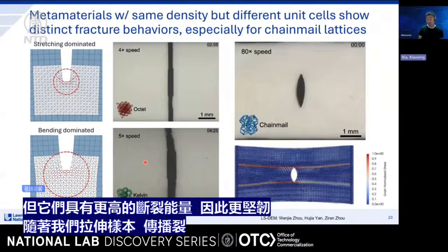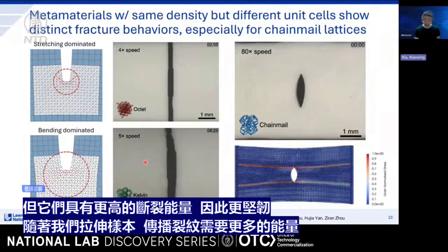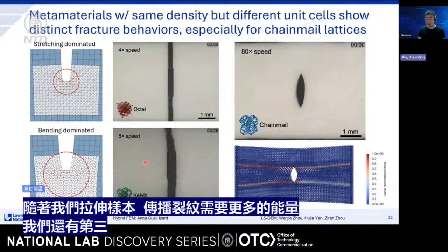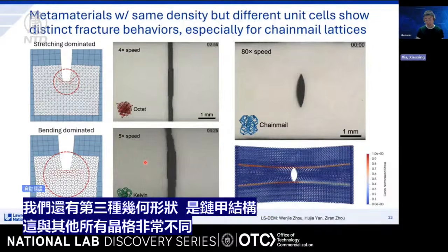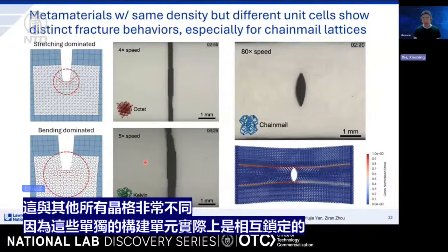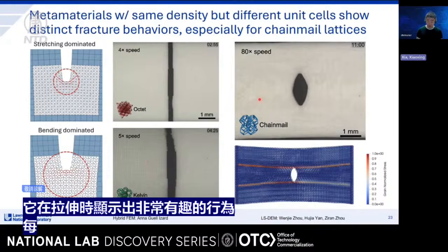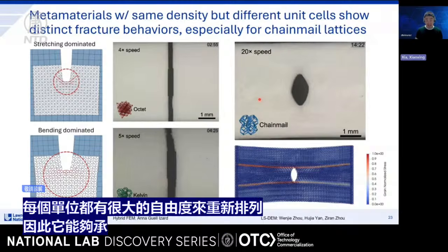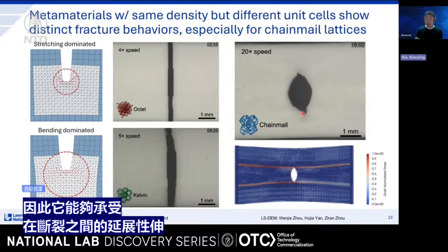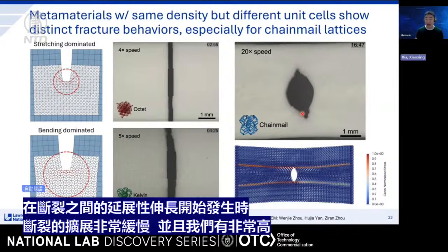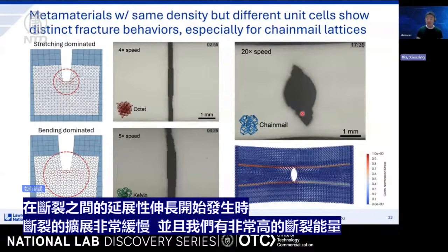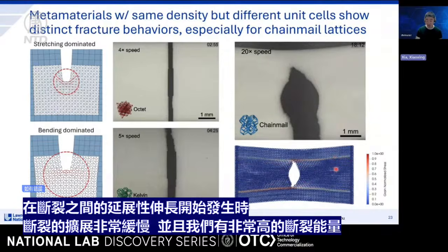And we also have a third geometry that is a chainmail lattice. This is very different from all the other lattices in the sense that those individual building blocks actually interlock with each other. So it shows very interesting behavior as we uniaxially stretch it. Each individual unit has a lot of degrees of freedom to rearrange. So it can withstand extended elongation before fractures start to happen. And when it happens, it propagates very slowly, and we have a very high energy of fracturing. So we did very detailed modeling of this behavior.